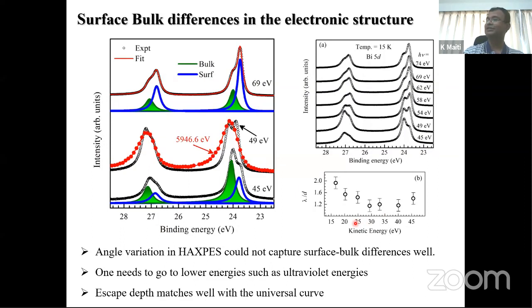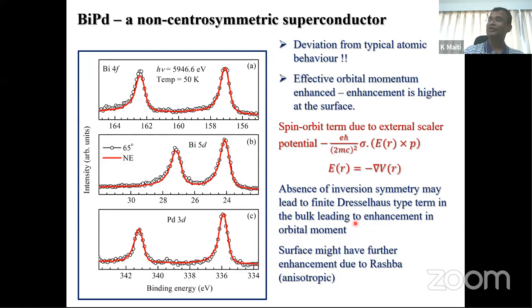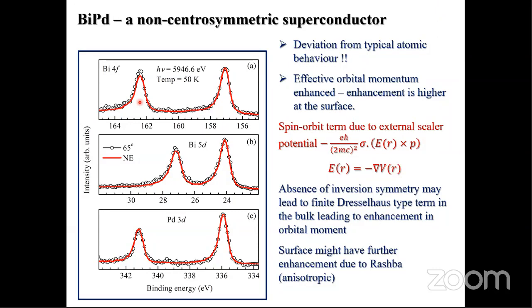So that's one thing. But the most problematic thing that we found is that normally, if you look at, say, bismuth 4f, the intensity ratio of this peak and this peak should be, so this is 7/2. So if you make it 2j plus 1, which is 8, and this one is 5/2, this is 6. So the intensity ratio would be 6:8, which is about 3:4.